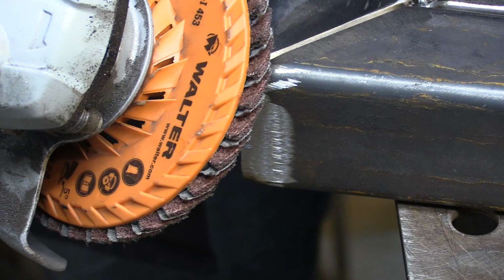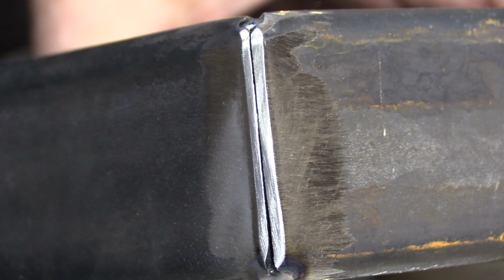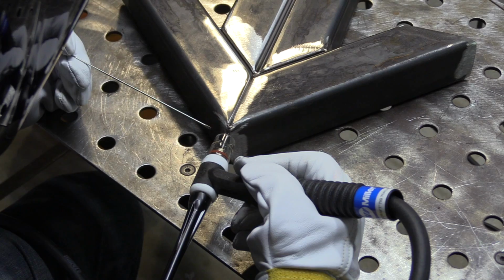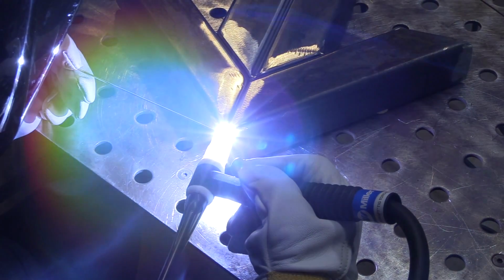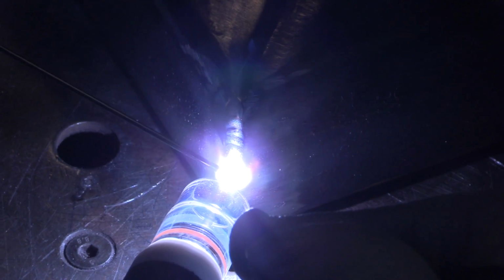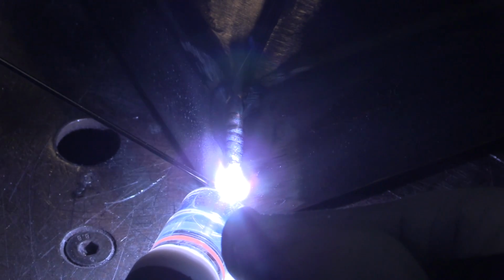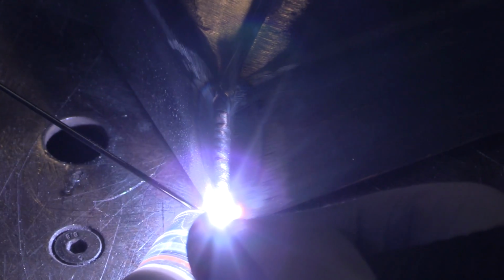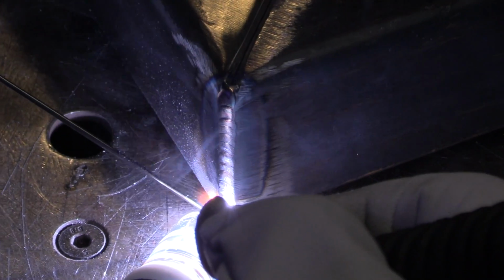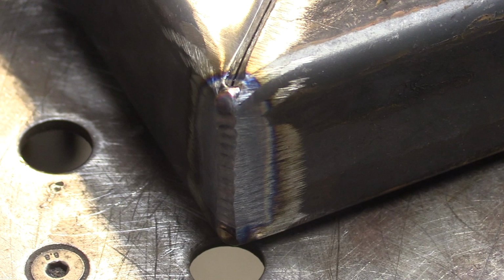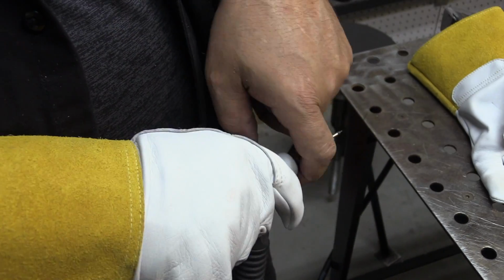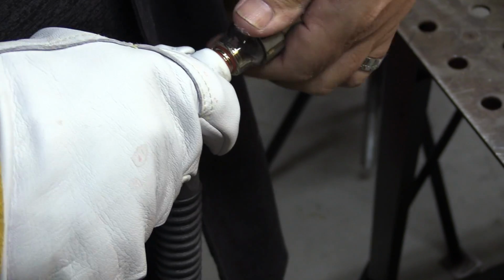All right, this corner, I'm going to go ahead and knock the corner off because I think that's a good idea for an outside corner like that on a sharp angle. It just welds better when there's a little area for a bead to go instead of trying to fuse those sharp corners together. Either way works, but I like to add a little filler on carbon steel. It doesn't fuse quite as cleanly as stainless. No deoxidizers in that metal really, and it can sparkle and spew and get porosity by fusing it with no filler metal. So downhill seemed to make sense after knocking that edge off with a flap disc.